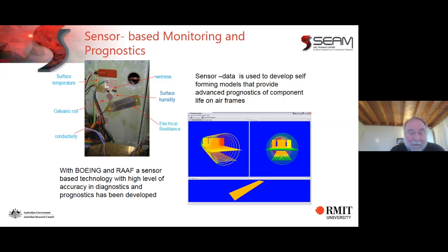This, in fact, is a C-130, where we placed sensors in this mock-up and put them in the lab, and had the same sensors in a C-130 transport aircraft. This is one of the problems implicit in this, which we'll talk about later, is these sensors are quite large and they're actually not measuring explicitly the corrosion of the surface. They're measuring corrosion on little coils or little bits of metals that we hope will simulate the surface. But we can measure the microclimate and the corrosion rate in the surface.